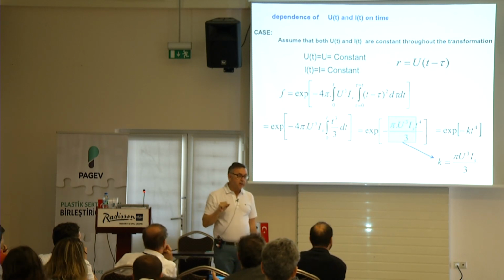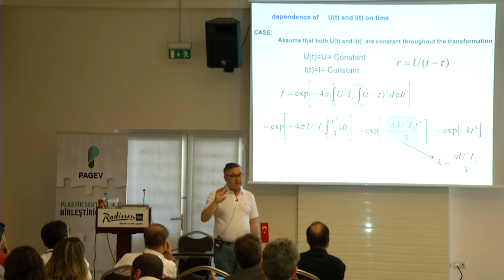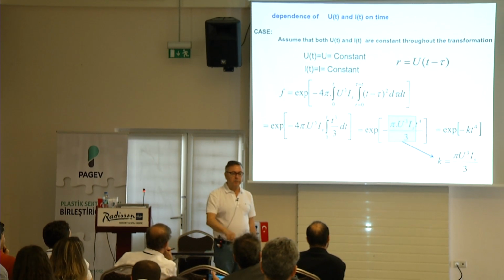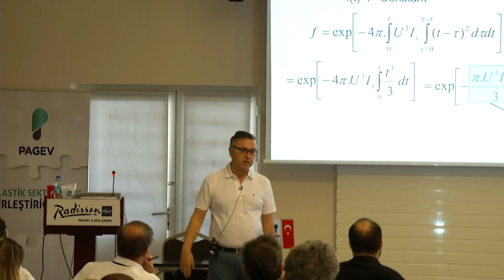So if you want to crystallize the material inside a mold faster, that's another tool. Lower the molecular weight. Lower molecular weight, faster diffusion, faster crystallization completion, faster ejection, if you can afford the reduction in mechanical properties. Everything is compromised, right? You want to go high production rate, or you want to go high strength materials. So what you do is you optimize. High enough molecular weight, but not too much, because higher molecular weight means it's going to slow down your crystallization process.